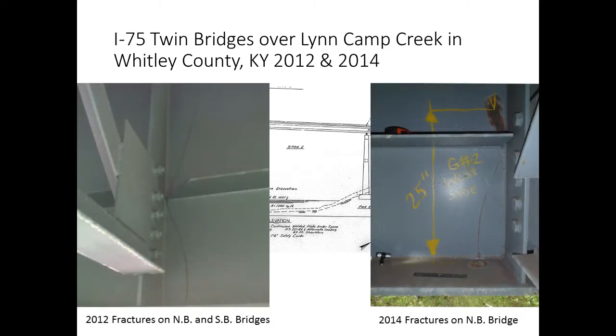And in 2012, both the north and southbound bridges experienced single fractures, seen here. You can see we've got the vertical stiffener, and then we've got the horizontal stiffener, and we have this narrow gap area there where the welds intersect, giving us that high constraint. See the cracks run up and down below the horizontal stiffener. So our suspect area for crack initiation would be right in here.